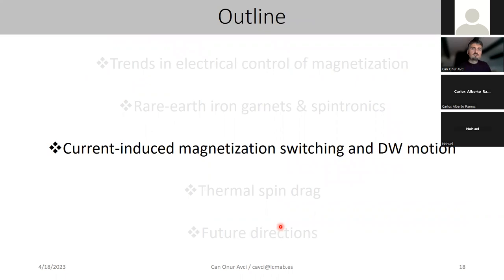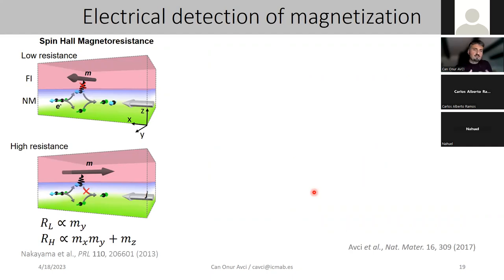Okay, so now let me show you some results on the current induced magnetization switching and domain wall motion. We would like to do current induced switching and detect the magnetization state by electrical means. But first, we need to be able to detect this magnetization using simple electrical measurements. For that, thankfully, we have this effect called spin Hall magnetoresistance. You might be familiar with it, but in a nutshell, if you have a bilayer system consisting of a normal metal like platinum and a magnetic insulator, like a rare earth iron garnet, an insulating magnet,